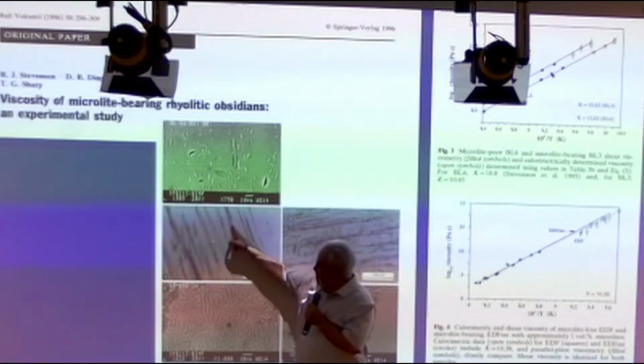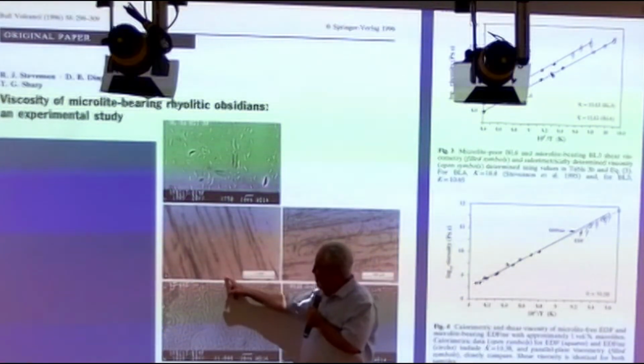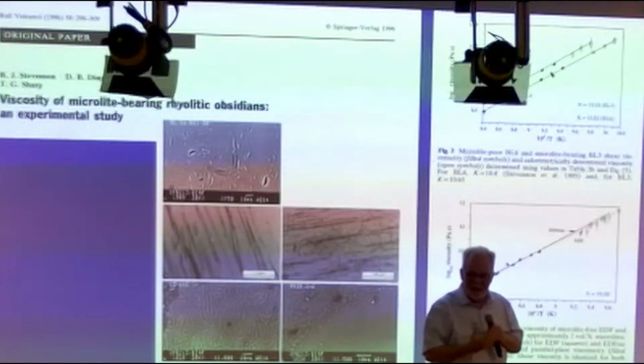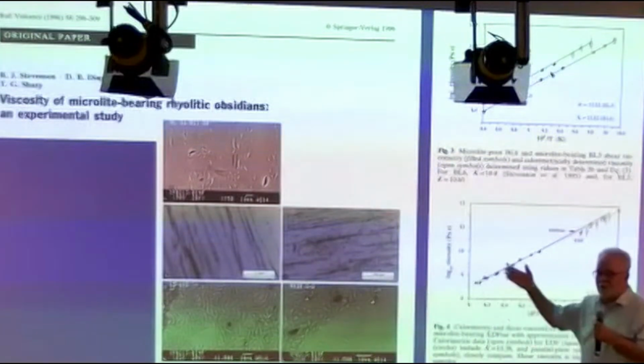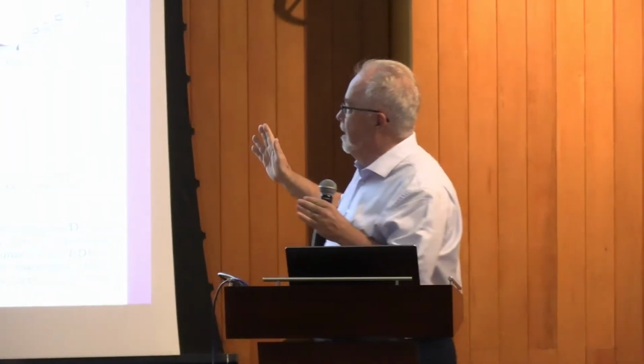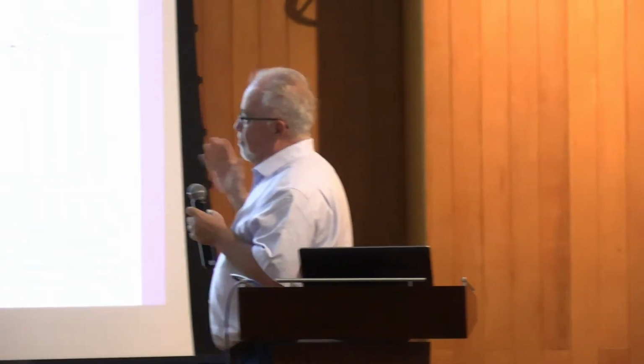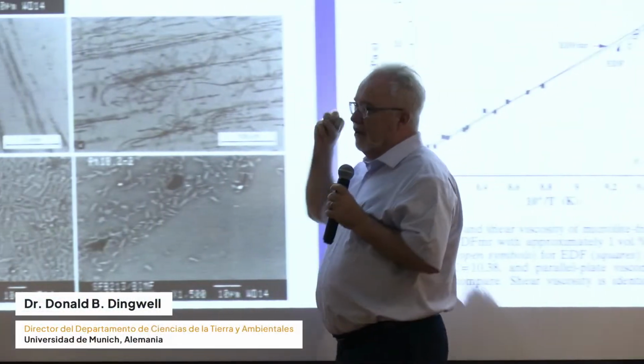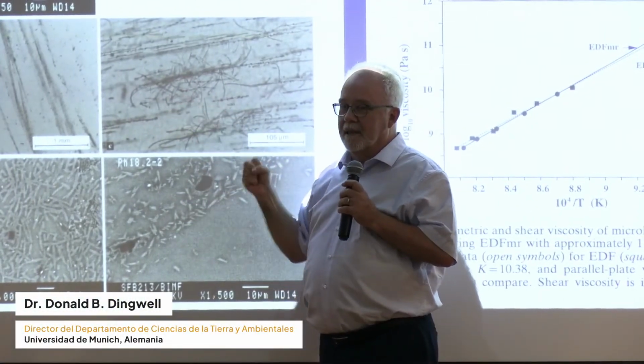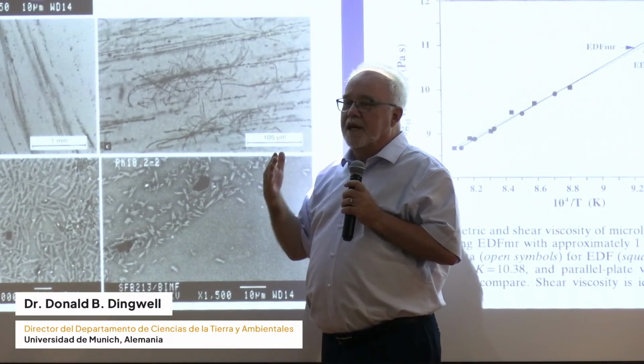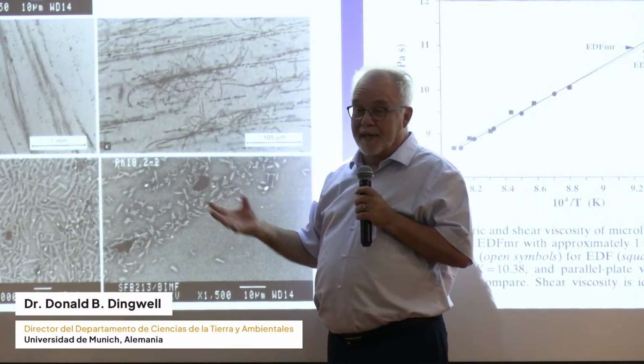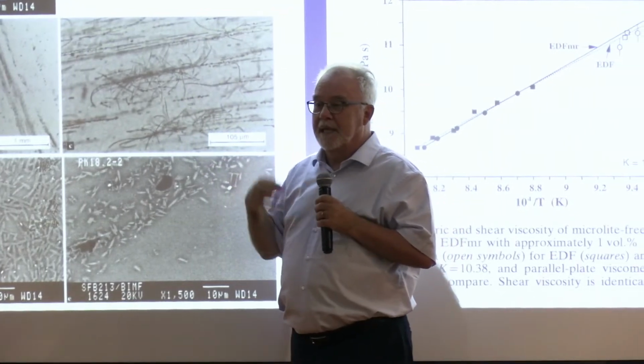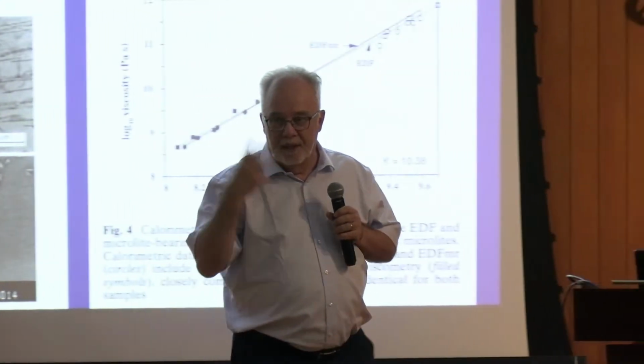Because how do you explain this? You have microlites which are lined up as if they're sheared out. Why aren't they homogeneous throughout the glass? What mess is this? I mean, your first reaction is either beautiful or really ugly, right? Because you can't explain it. So what we think in the meantime for all of these things is that these are things which have fragmented and healed, fragmented and healed. And when they've healed, there's been a loss of pressure, there's been a loss of gas. Suddenly they jump to the side in terms of stability, and these microlites start to grow.